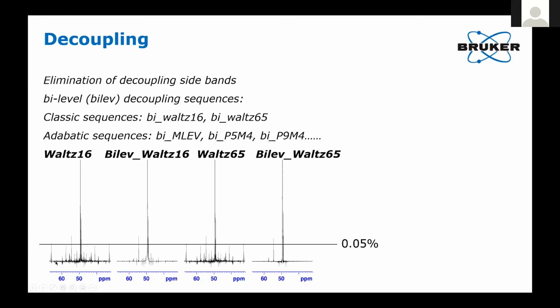If we start with our WALTZ-16 here, which gives us this decoupler sideband pattern, we go to a bilevel WALTZ-16, we can see that we can eliminate a lot. But if we take the WALTZ-65 and do a bilevel WALTZ-65, using this stepping of the decoupler sequence into the acquisition, at our 0.05% level here, we get this much lower.